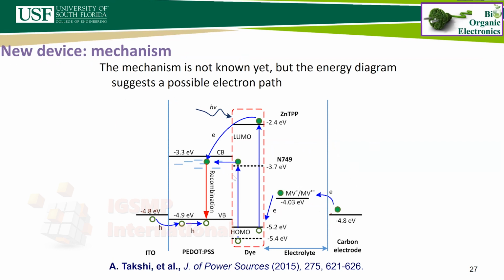But investigating this diagram, we learned that perhaps the conducting polymer PEDOT:PSS that we have been using was not necessarily the best choice for that. So we looked at a different conducting polymer, polyaniline, and particularly we chose this polymer because it does have multiple redox states. It can go from emeraldine to pernigraniline or leucoemeraldine, depending on whether you are giving or receiving electrons.